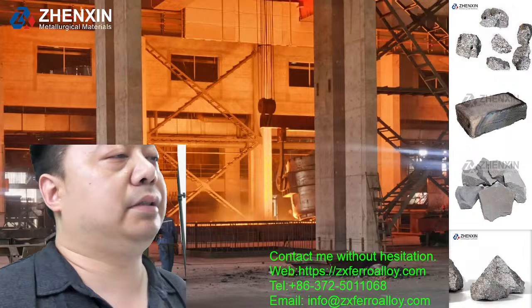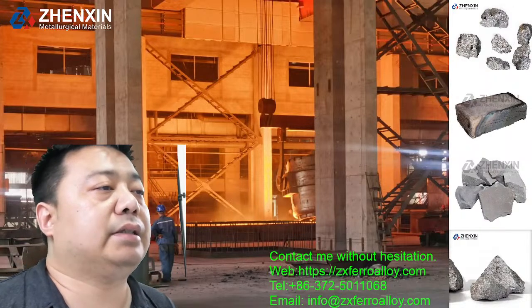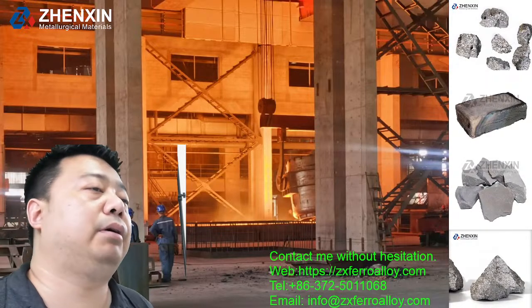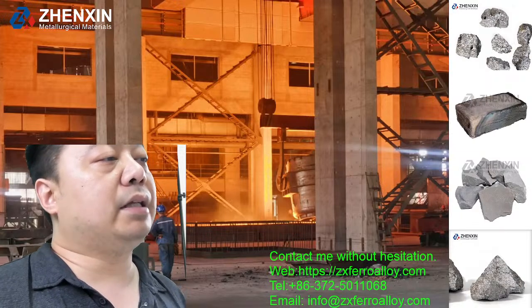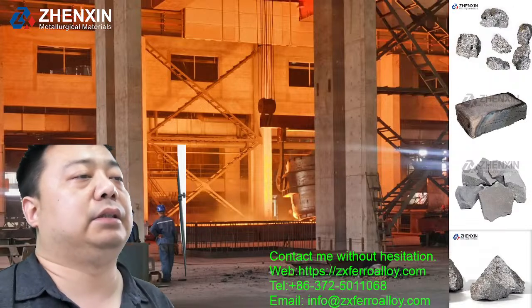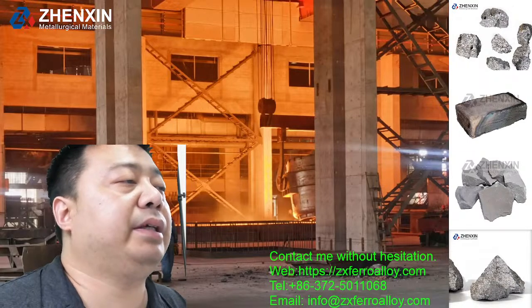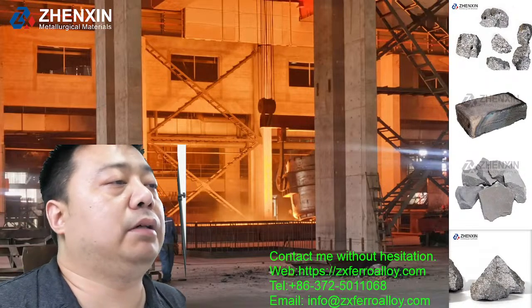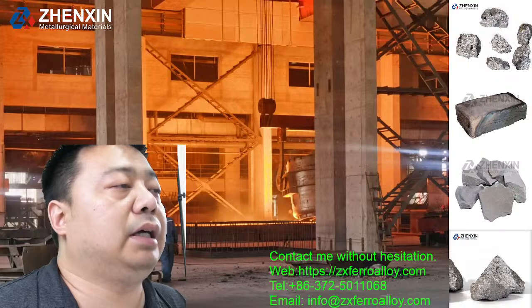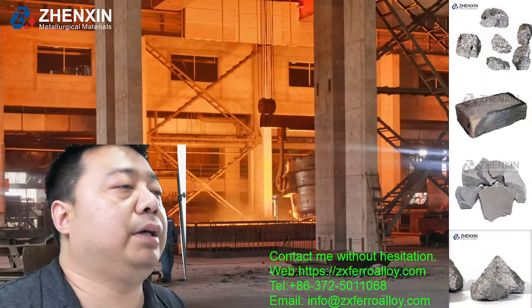28% to 35% calcium particles and 65 to 72% iron powder as a core material. And the inner core is wrapped with a cold rolled low carbon steel strip. As major oil and steel companies have strict requirements on the form and quality of low carbon steel, ultra low carbon steel, low silicon steel, and other inclusions, calcium iron cored wire is generally selected for calcium treatment of crude steel.